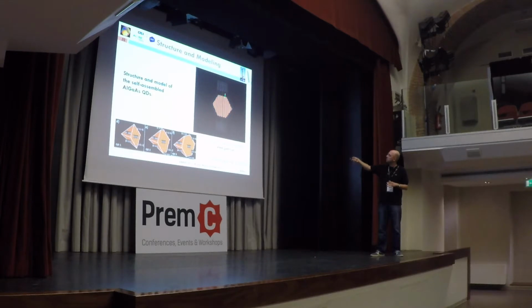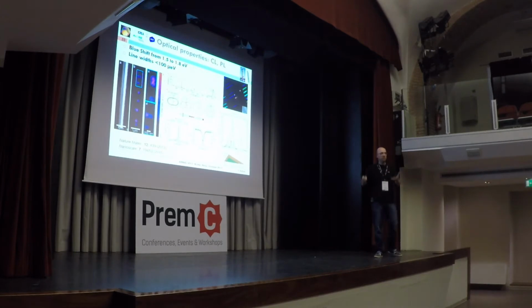This is the edge terminated in 112, and this is a kind of pyramid, not exactly, but it has this shape. It's a little bit more complicated. Just inside, you have a quantum dot that is gallium-rich. Okay? So with this material, you can do photoluminescence, you can work in cathodoluminescence as well, and you can see the single photon emission that is produced by these quantum dots. You cannot control exactly where these quantum dots are formed, because these are kind of defects, but you can assure that in every nanowire or every nanomembrane, you can find at least several of these quantum dots.